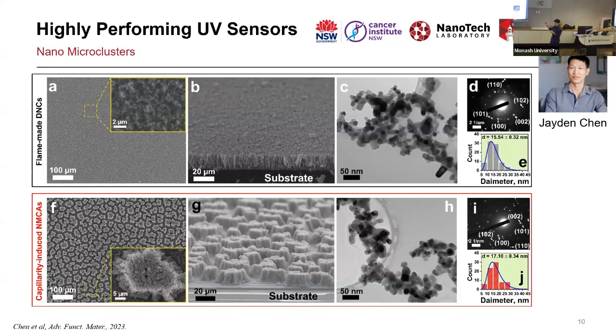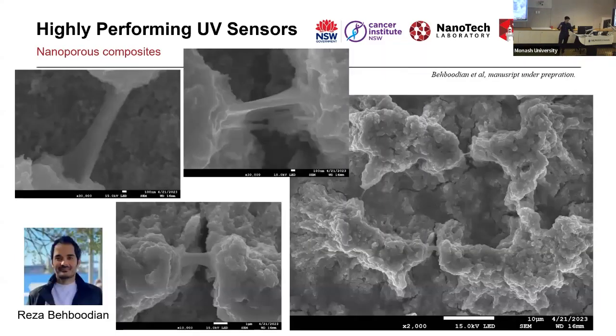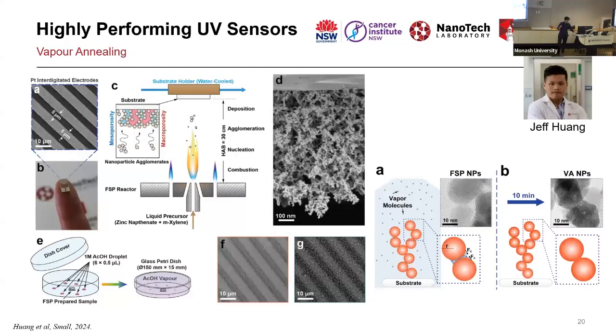Yeah. So the key here was to not destroy the structure, but also at the same time improve it, or at least have the structure stay the same, which in the case of the vapor, the structure didn't change significantly. A little bit in terms of the transparency, but in terms of the morphology, the macrostructure is very similar. It's just a bit shrunk, but we still got a significant improvement in terms of connection between the particles. So that welding happens because of the condensation and fusion.